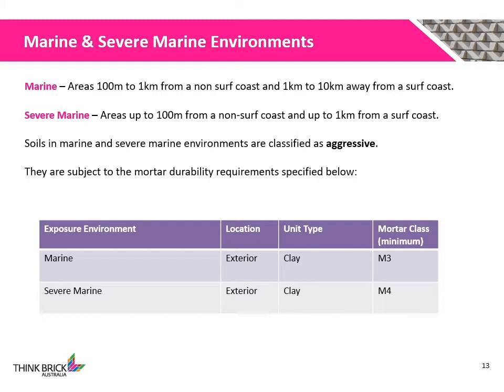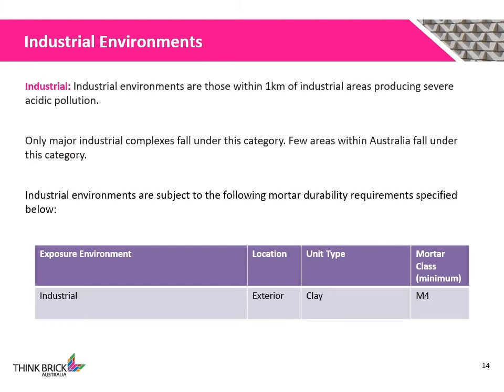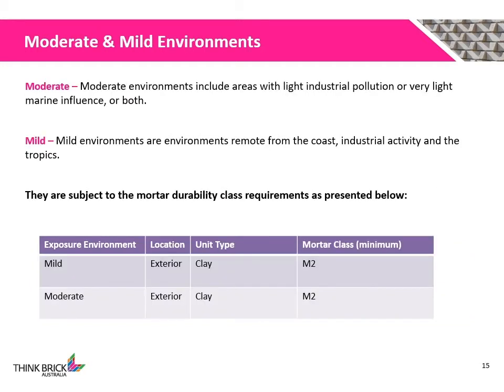Severe marine environments are defined as areas up to 100 m from a non-surf coast, and up to 1 km from a surf coast. M4 mortar shall be used for these environments. The soil in marine and severe marine environments is classified as aggressive. Industrial environments are defined as areas within 1 km of major industrial complexes producing severe acidic pollution, and M4 mortar shall be used for these areas. Moderate environments are areas with light industrial pollution or very light marine influence, or both. Mild environments are areas that are remote from the coast, industrial activity, and the tropics. M2 mortar shall be used as the minimum for these environments.